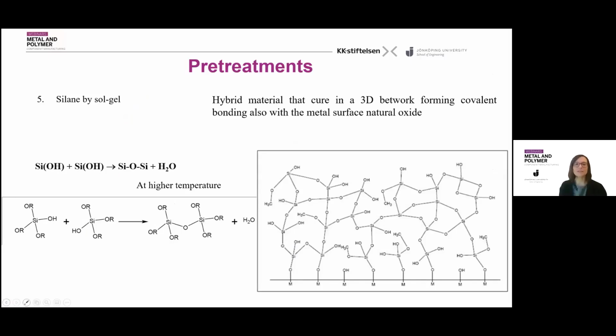A little bit different pre-treatment is given by silane. Silane is a hybrid material, organic inorganic material, based on silicon and silicon oxide bonding that can react at high temperature to create a network of structure.